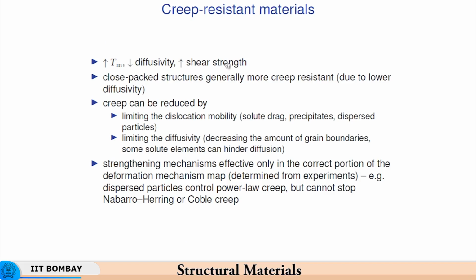So, if you consider making materials resistant to creep, then at increased temperature we should have low diffusivity, because diffusion controls the rate, and therefore we should reduce the diffusivity to the extent possible and increase the shear strength of the material. Now, close packed structures are generally more creep resistant due to lower diffusivity.